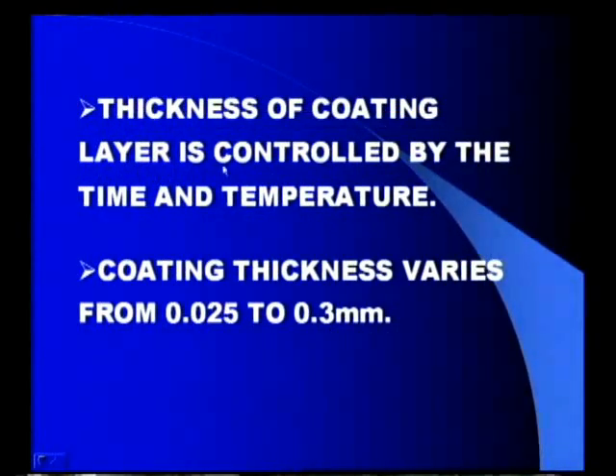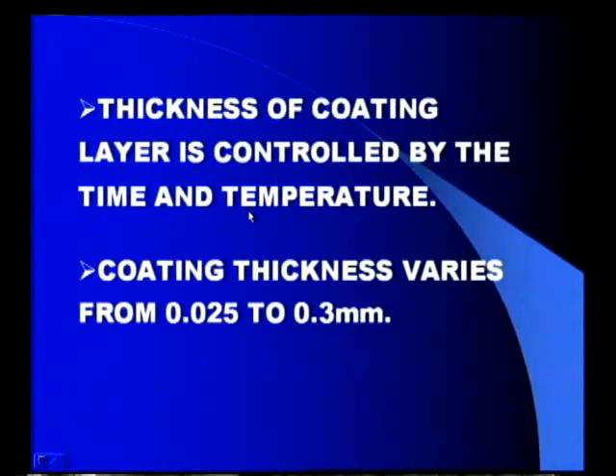Now, the thickness of the coating layer is controlled by the time and temperature. Naturally, in this kind of method, that is hot dipping, the thickness of the coating layer is controlled by the time. The more the time, the higher will be the thickness. But when you keep it for a very long time, naturally the material becomes brittle, thereby further bending and forming of the coated part will be a difficult task. Therefore, there is a restriction on the upper side of the time and also of temperature. So correct time and temperatures are chosen for the required application.